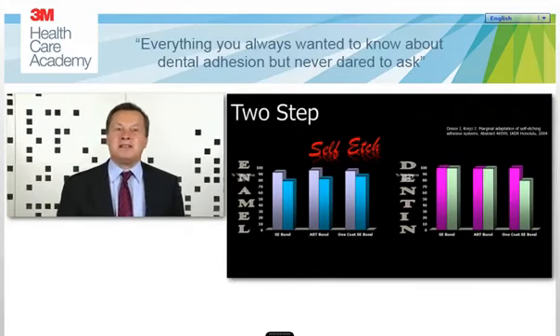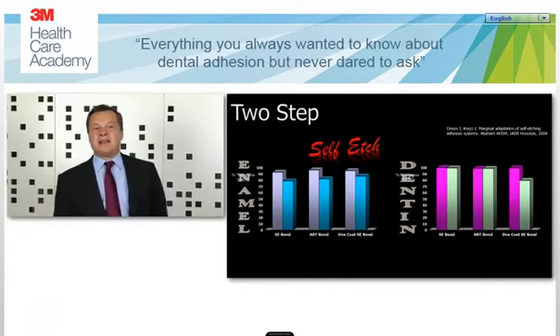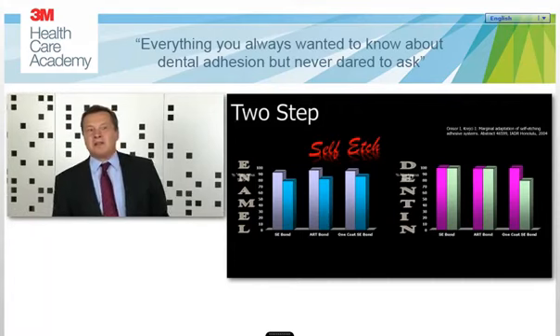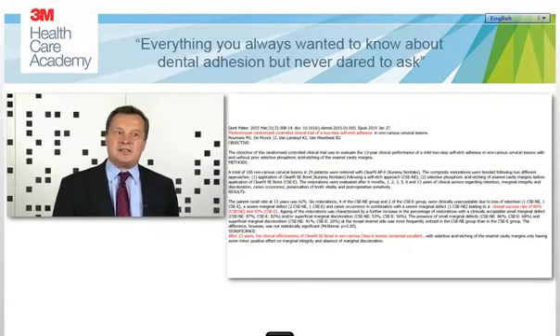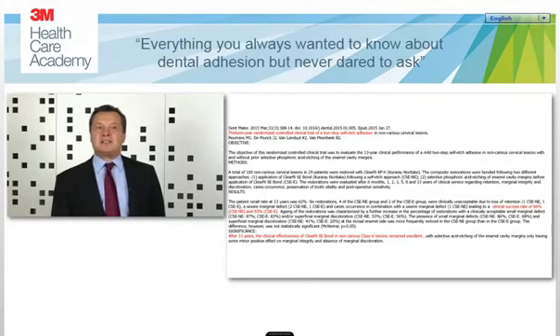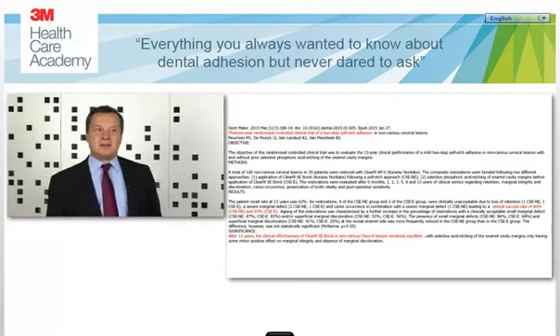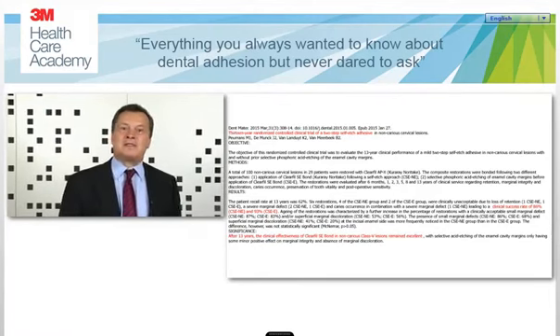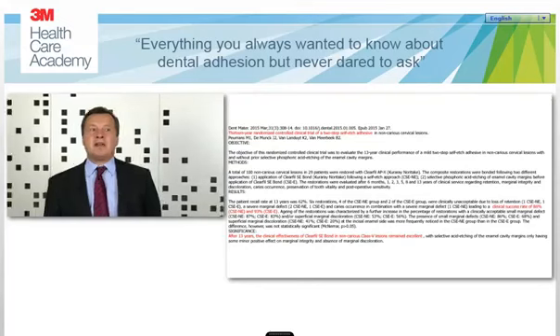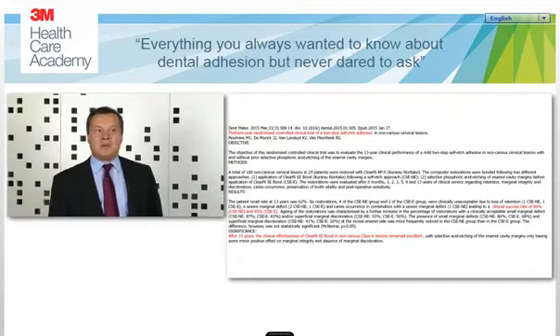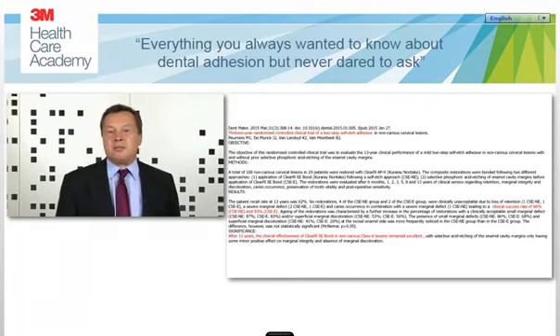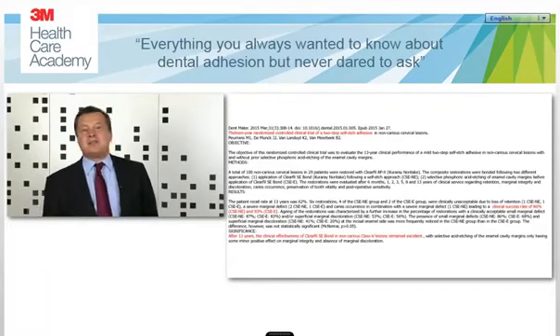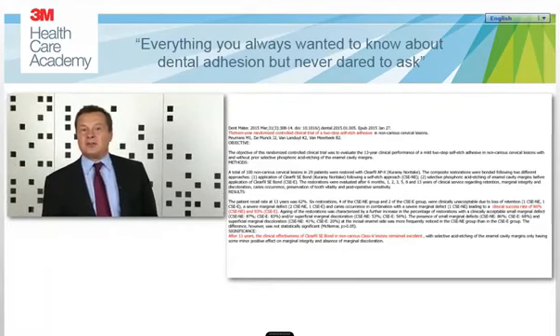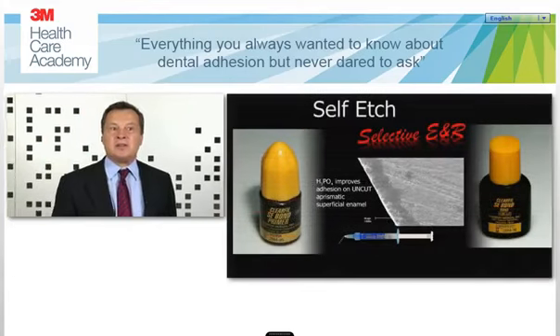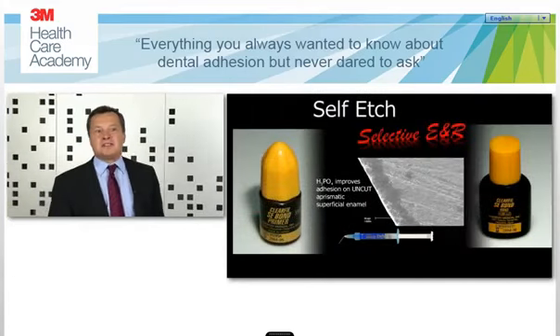And you can see some other adhesive systems, self-etch adhesive systems on this slide, and they behave pretty well and very, very similar to SE Bond. So it seems that there's no real difference between the classic gold standard three-step adhesive systems and these already simplified self-etch adhesive systems. And this was also very, very recently confirmed by a study from the same group, again, the group of Bart Van Meerbeek, where he tested a self-etch system after 12 years. And he found out that the results are really comparable to the results after this period of time for Optibond FL. So even clinically, no difference, which at the end confirms our results from our in vitro test. Just a small detail on self-etch systems.